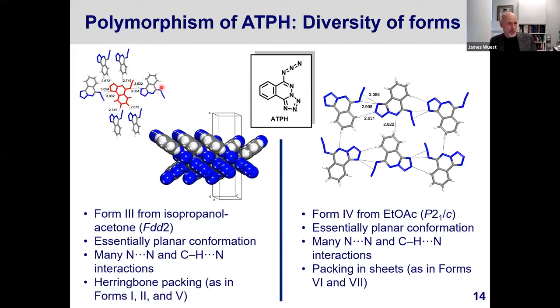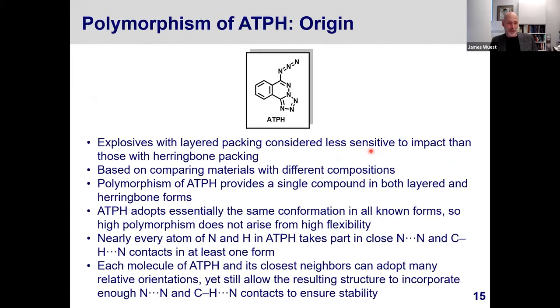Again, as I said before, the conformation is essentially planar. There are many different NN and CHN interactions involving the tetrazole, the azide group, and the 4 CH hydrogens of the compound. The packing in this particular case is herringbone, and that is also the case with forms 1, 2, and 5. So roughly half of the structures adopt this type of herringbone pattern. The other half, illustrated here by form 4, crystallized from ethyl acetate, again essentially planar, again many NN and CHN interactions, but the packing forms sheets. So there is a striking diversity in the different types of forms that can be produced by the crystallization of this relatively simple molecule.